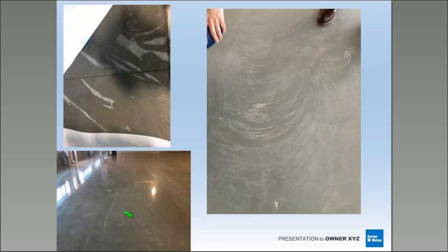Hey, we have wheels for riders, guys. We have wheels for walk-behinds. Don't fire them up and run them across the floor, because this is exactly what you're going to end up with, scratching and gouging. This actually looks to me like they blew out a pan in their process of finishing and never refined the floor. They got on it too late.